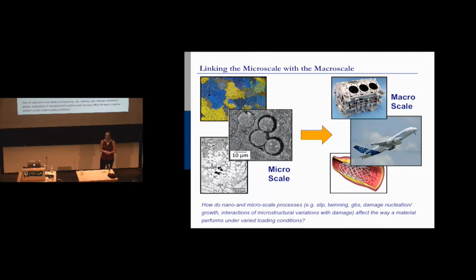If you think about how much scatter fatigue has, it has a lot of scatter, right? You look at fatigue data, and it's very scattered, so you need many, many, many specimens. So we were interested in accessing this range. What happens is the stress life curve comes down like this, and you can use the traditional laws over here. When you get to 10 to the 9th cycles, if you go out that far, you'll see a dip again, and you'll see a drop off in how long the lifetime is.